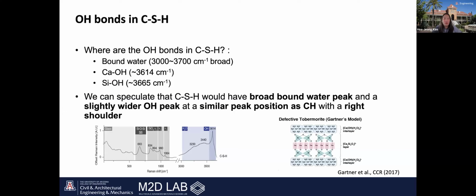From the CSH spectrum, three types of OH bond can be identified: bound water, CaOH, and SiOH. Based on this observation, we can infer that CSH exhibits a broad bound water peak and an OH peak slightly wider than that of CH, with a right-hand shoulder, suggesting structural complexity. Numerous structure models for CSH have been proposed, and our Raman spectrum strongly supports Gartner's model, which describes CSH as a disordered layered structure containing both CaOH and SiOH bonds.